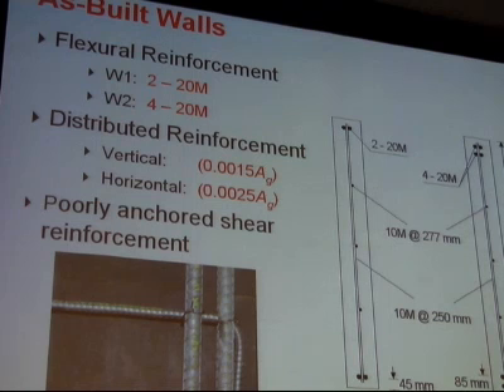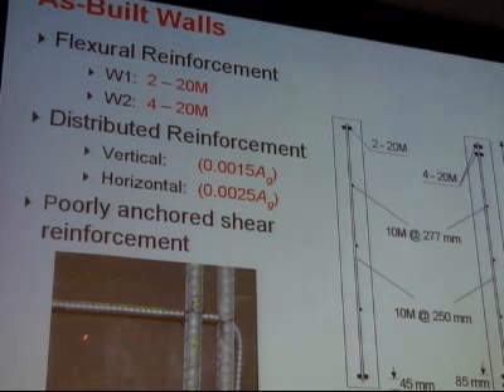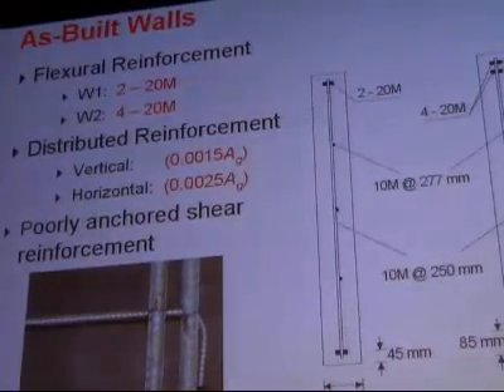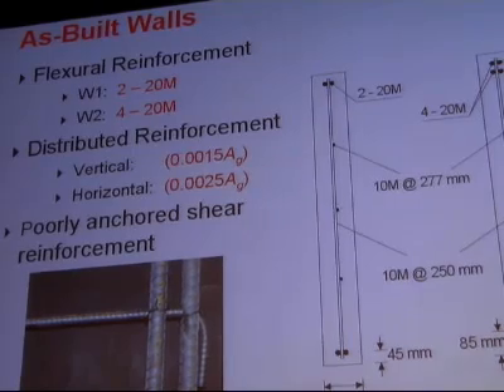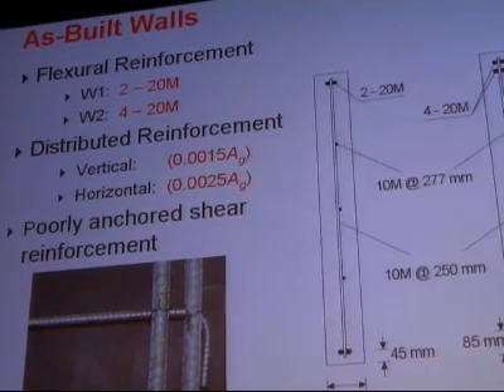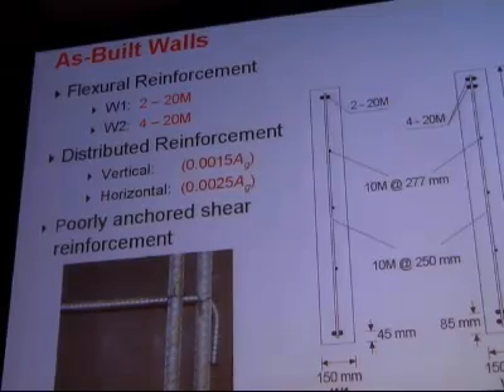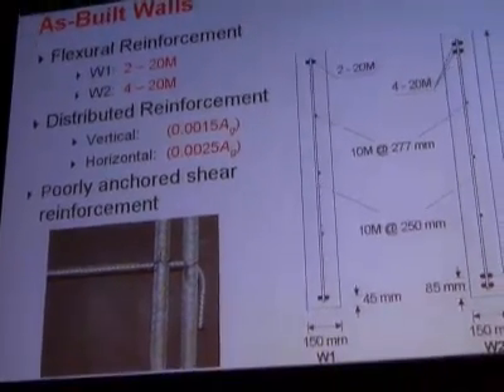And one of the problems when you have a very thin wall, 150 millimeters thick, is that there's no way to anchor the horizontal reinforcement. So typically they would put a 90-degree bend without bending it around the reinforcement at the ends of the walls. And of course, that's totally inadequate. We did 2 walls in the as-built condition, one wall with 2 20Ms at each end, and one wall with 4 20Ms at each end. And these have the lap splices, and they have typical amounts of vertical and horizontal uniformly distributed reinforcement.